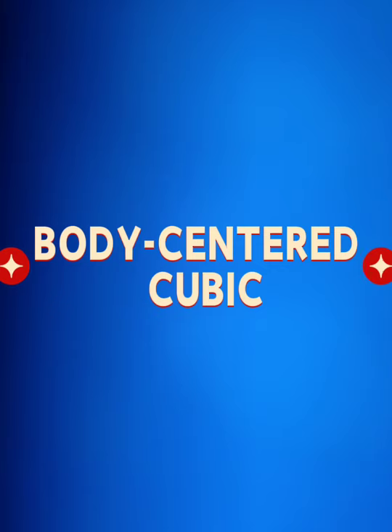So let's proceed to the second one, the body-centered cube with a packing efficiency of 68%. As you can see, there are 2 atoms per unit cell. Every atom at the corner is 1/8 of an atom. So, 1/8 times the number of corner atoms plus 1 whole atom at the center equals 1/8 times 8 is equal to 1, plus 1 is equal to 2. Therefore, there are 2 atoms per unit cell.